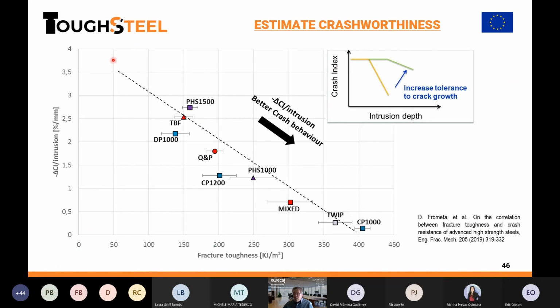Okay, if we put this crash index for different materials, we see that the higher the toughness, the higher the crash resistance. Because what we want here is that the crash index decreases in a slow way. Because if it is in a slow way, it increases the crash resistance. So decreasing the slope, increasing the fracture toughness.